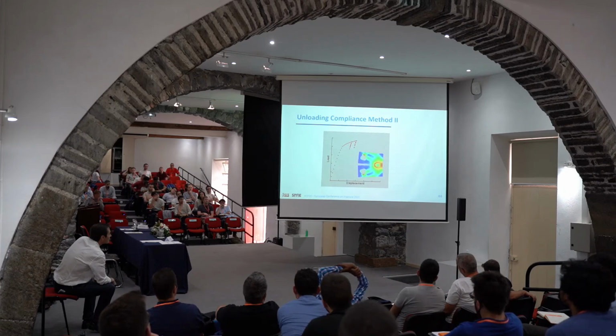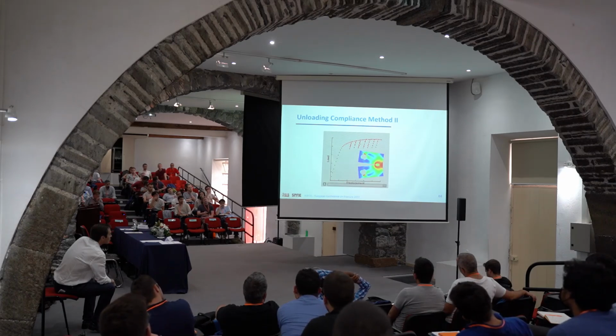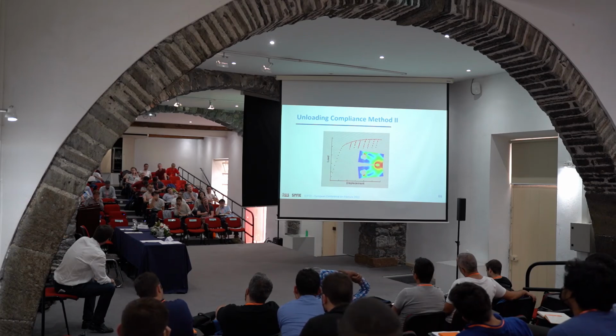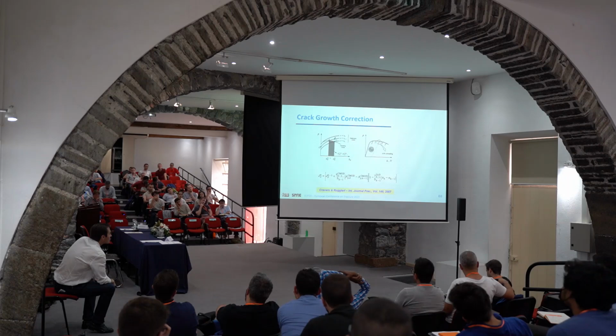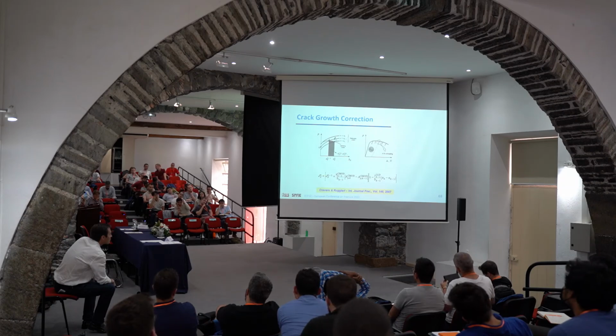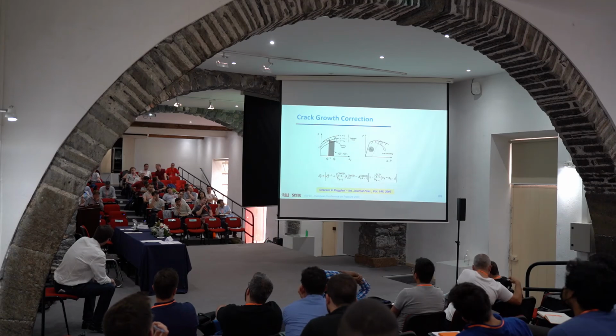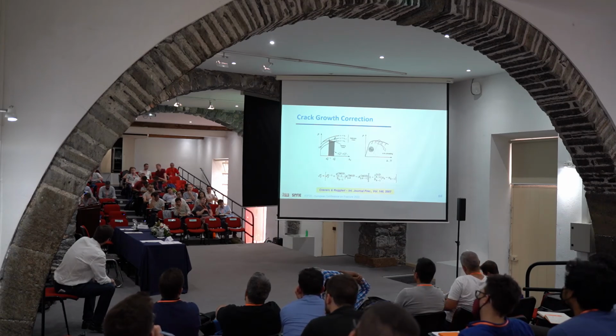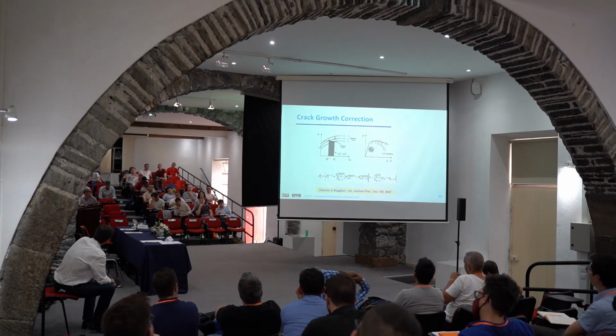Load, unload. And since the crack is growing, you cannot see it with your naked eye, of course, because the variation is very small. But the slope of the elastic unloading is varying, so we correlate the variation in the elastic unloading with the variation in crack size. That's how we usually do it. We can use other techniques, of course, for example potential drop. We can set up an electrical device and measure the resistivity, because when the crack is growing, the resistivity is also changing. Then we calibrate the change in resistivity against the change in crack growth.